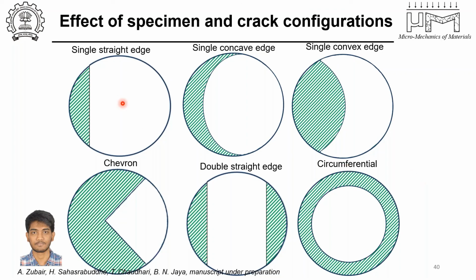Now, of late, we have also been looking at various other crack configurations, so the single straight edge created these problems. So we wanted to see what happens to the double straight edge versus circumferential crack configuration. We also wanted to see what happens when you have a convex or a concave edge crack, because when you cut a specimen, it's difficult to achieve a straight notch. Especially when you do it with the laser, you end up getting a notch which looks like this. So we wanted to look at different configurations, and the chevron is something that has been used in fracture toughness testing, so we wanted to also explore that.